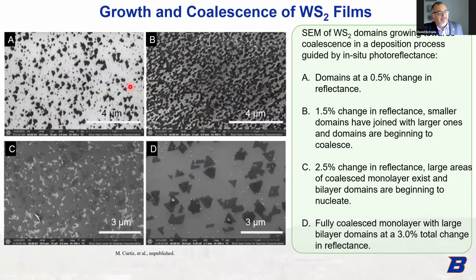Here's the evolution of the growth, looking at different SEM images from 0.5 to 2.5 or 3% photoreflectance change. We do get fully coalesced WS2 over our 50 millimeter sapphire wafers, but we do end up with about 18 to 20% bilayer coverage. That's just through image analysis, looking at the image contrast, right?